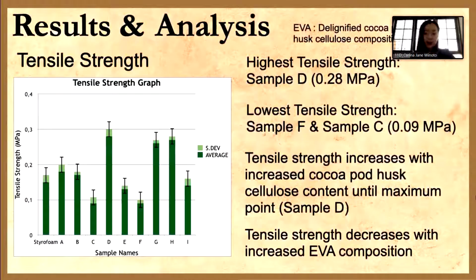For tensile strength, the highest value was found within sample D at 0.28 megapascals, while the lowest was found within sample F and sample C at equally 0.09 megapascals. Since tensile strength refers back to the maximum load and maximum stress samples can withstand without being elongated prior to fracture, it can be stated that sample D is able to withstand the greatest amount of load and resist the greatest amount of tension compared to all samples, especially to sample F and C, which can only hold up to